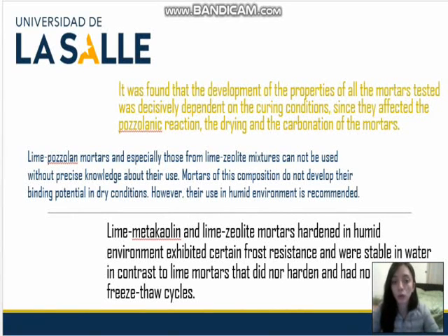Okay, and the conclusions. It was found that the development of the properties of all the mortar tests was decisively dependent on the curing conditions, since they affect the pozzolan reactions, the setting, and the carbonation of the mortars.